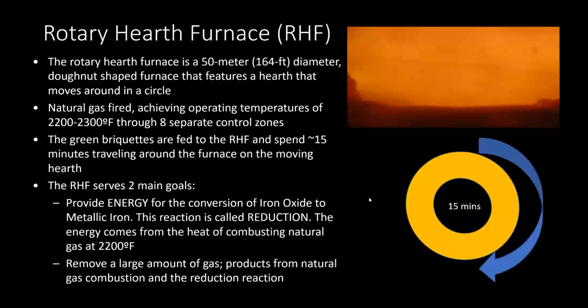So talking about our rotary hearth furnace, it's a fairly large furnace, 50 meters in diameter, 164 feet. It's donut shaped, so the steel or the pellets get loaded on a bed and go around the furnace. It takes about 15 minutes. It's a gas-fired furnace, running between 22 and 2300 Fahrenheit.